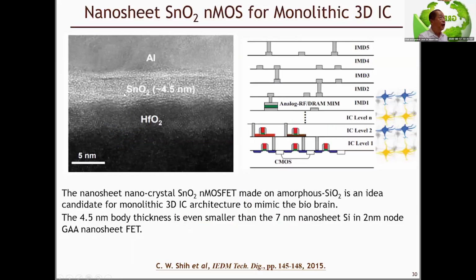The nanosheet SnO2 nMOSFET made on amorphous silicon dioxide is an ideal candidate for monolithic 3D architecture to mimic the bio brain. The 4.5 nanometer thickness is even smaller than the 7 nanometer nanosheet silicon in the 2 nanometer nanosheet FET used in production this year.